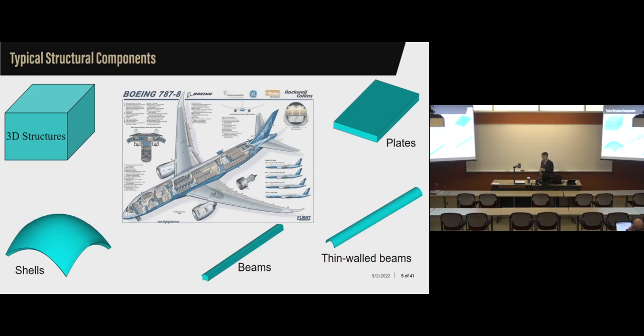And that's when I first tackled the multi-scale problem. I tried to think from the system perspective. That's where my PhD training was. I dealt with the whole helicopter system, so it's at the system level. When we look at a complex system like the Boeing 787, when you do structure analysis, you idealize it as a combination of 3D solids, plates and shells, beams and thin-walled beams. It depends on the geometry. If your thickness is much smaller than the in-plane dimensions, whether it's curved or not, it becomes a plate or shell. If one of the dimensions is much larger than the other two, it's a beam. Of course, that beam could be curved. And if all three dimensions are of similar size, it's a 3D solid. And if the three dimensions are orders of magnitude different, it's a thin-walled beam.